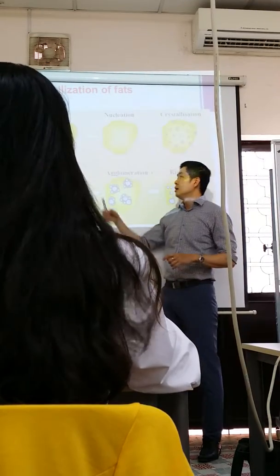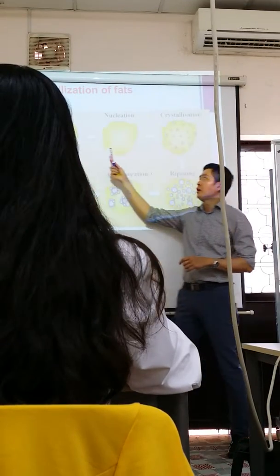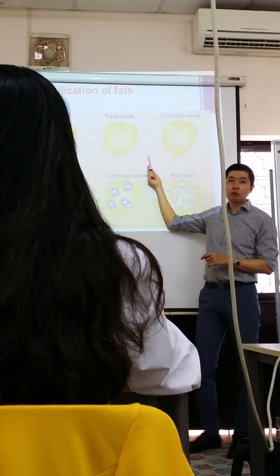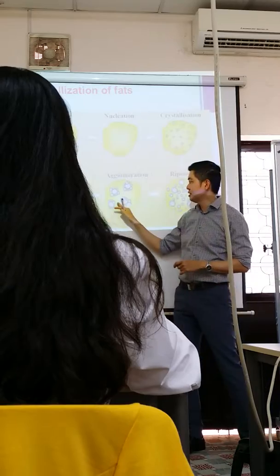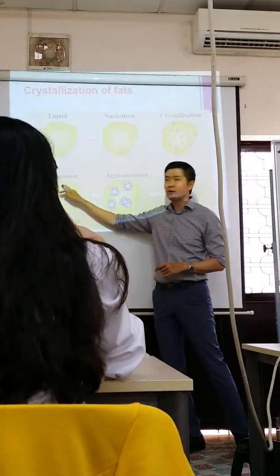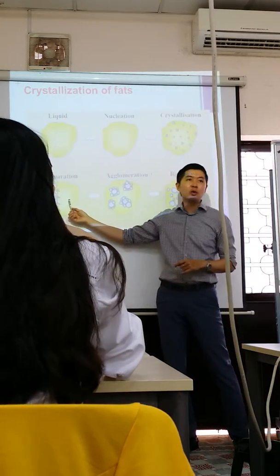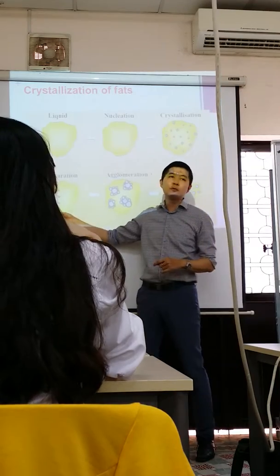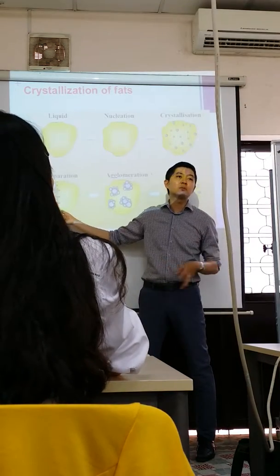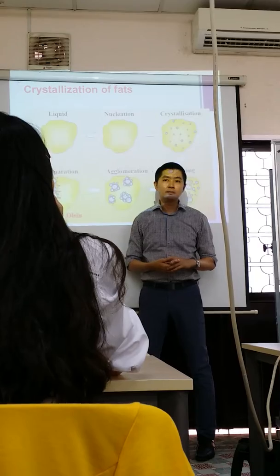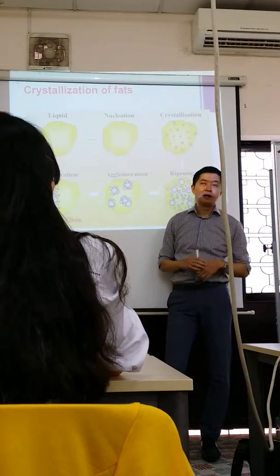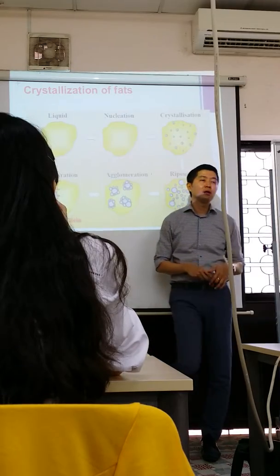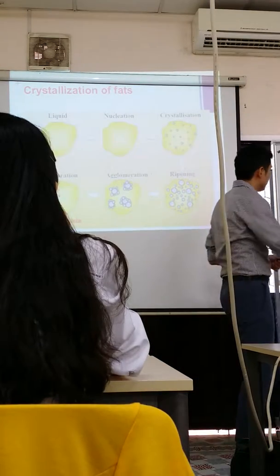Okay. Palm oil, you cool down a bit, they are going to go through this process until ripening, and then you have the stearin portion, and you have the olein portion. This one goes into cooking oil, this one will go into margarine and shortening production. Okay. So we will learn this process after refining. Okay, the whole process we call the fractionation process.